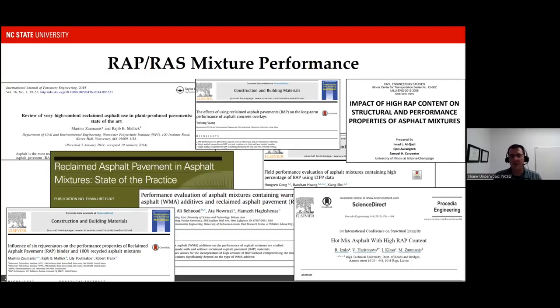Now, if you look in the literature, you can find literally thousands of papers on whether or not reclaimed materials perform better or worse. And the net outcome of all of those studies is it depends. Some studies find that reclaimed asphalt pavement materials perform adequately or equal to non-RAP materials. Some show that they perform worse. The general consensus is that RAP-based materials perform better when it comes to rutting and permanent deformation, but not always. There are plenty of studies that tell us something different. The consensus is also that RAP-based materials have the potential to increase the brittleness of our materials and therefore negatively